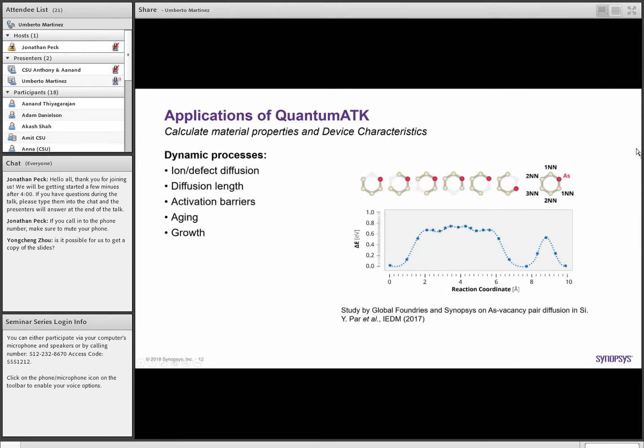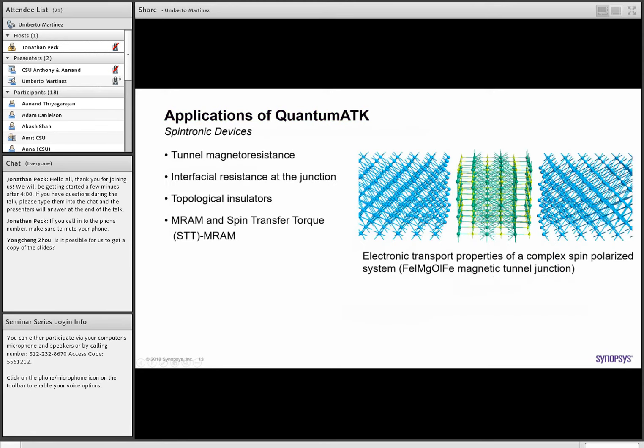You can study dynamic processes. For example, you can study diffusion of atoms, diffusion of molecules at surfaces, and calculate activation barriers, and this allows you to study aging, growth, and so on. In this example, we see the diffusion of arsenic and vacancy-mediated diffusion in silicon. So we can really understand how atoms diffuse in your material.